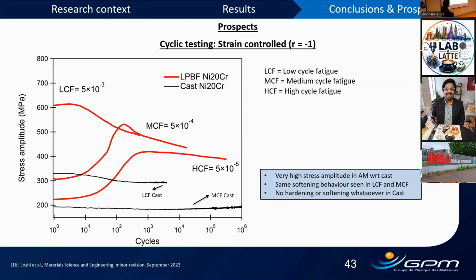So here we can see we did quite a bit of testing on LPBF and cast samples for low cycle fatigue, medium cycle fatigue, and high cycle fatigue in strain controlled conditions with completely reversed conditions. So the maximum strain and minimum strain are the same in magnitude. And here is the evolution of stress amplitude with respect to cycles. There is a lot of data here, but I just want you to look at two takeaways from this slide. One is if we compare the evolution of LCF for the LPBF sample, this red, and this cast, first, we see that LPBF increases fatigue resistance quite significantly.